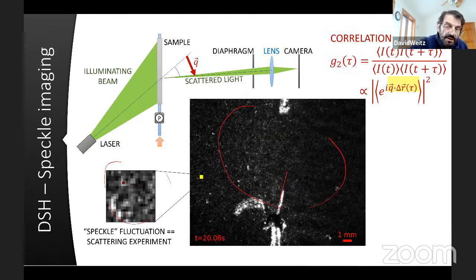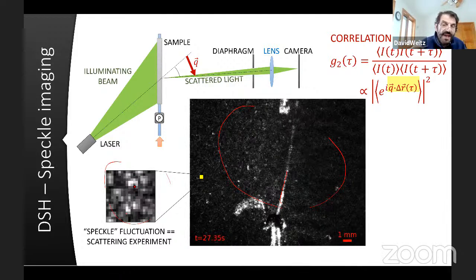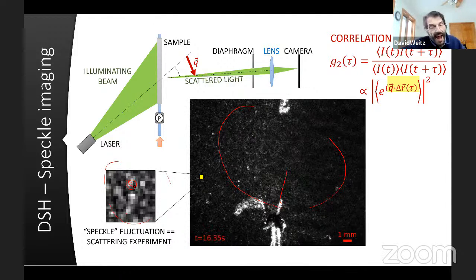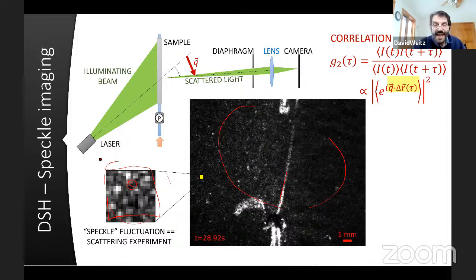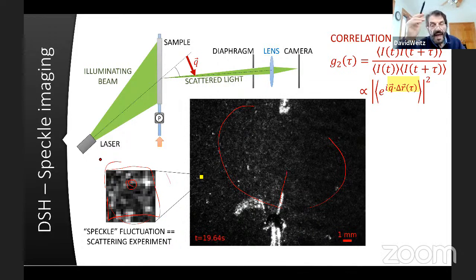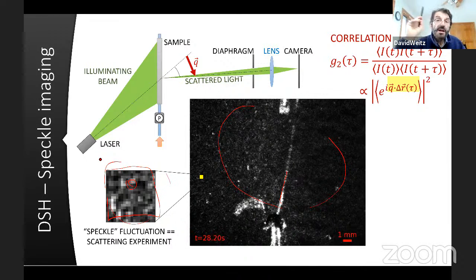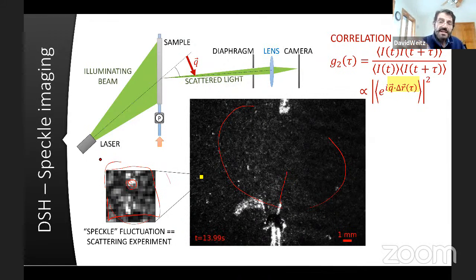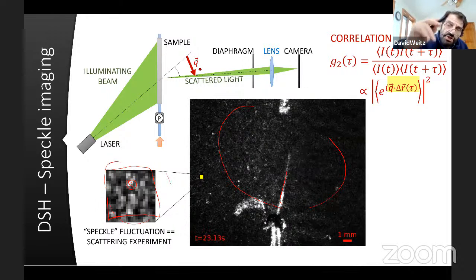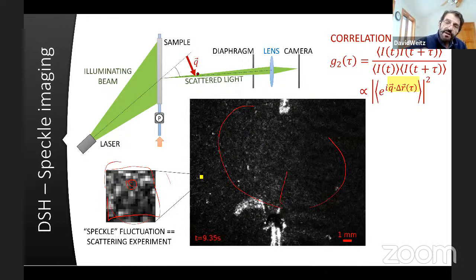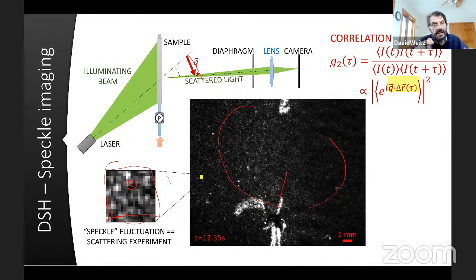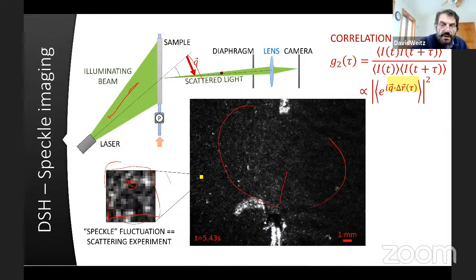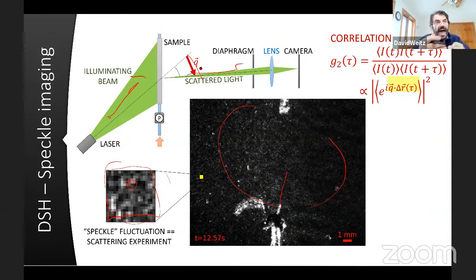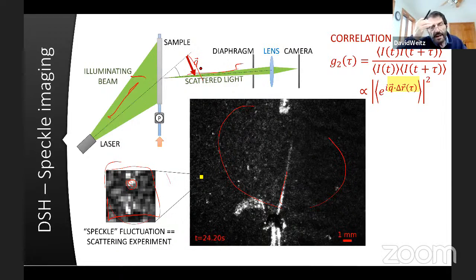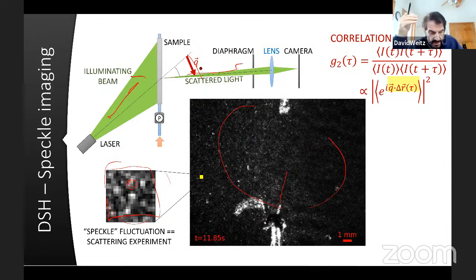And so again, you can just look at the correlations, and now all you have to do is measure the average intensity in one speckle. You can average over some region to get better signal to noise, but you just measure the initial decay of that speckle. What that tells you is there's motion. It also tells you the direction of the motion, because the change is always proportional to the scattering vector, the vector that connects the incoming light and the scattered light. The difference is the scattering vector, and it's motion along that scattering vector, so you have a directionality of the scatter.